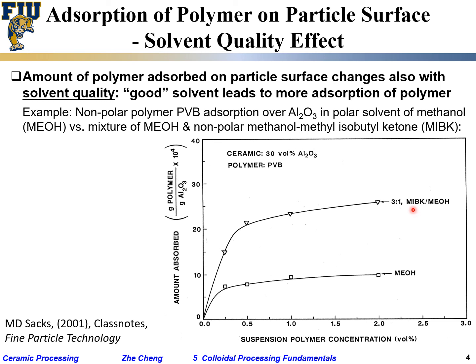So essentially, for the top one, we are adding less polar solvent, MIBK, and actually the majority of it would be MIBK. But I still have a little bit of methanol left. By making the overall solvent less polar, I'm having more adsorption of the PVB, not PVA, PVB onto the aluminum powder.